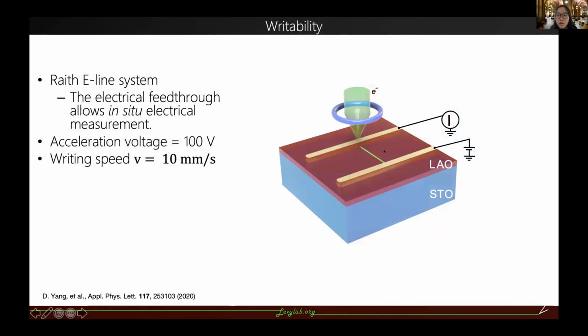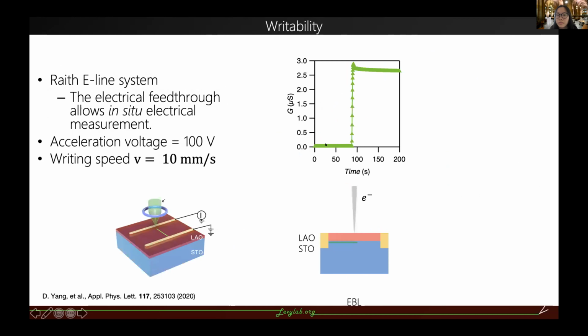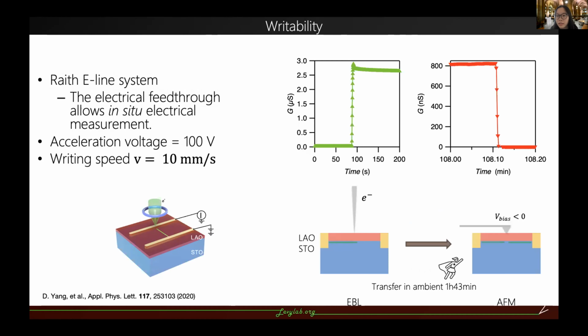This is to show the writability of this method. We have electrodes at the interface, and we expose a nanowire connecting these two electrodes using ULV EBL. With this writing process, we can observe a conductance jump from the writing. This is in situ monitoring. We added an electrical feedthrough to the SEM so that it allows in situ electrical measurement during the exposure. This writing process is also reversible. When I transferred it into an AFM and applied a negative voltage to the AFM tip to erase it, the device could be erased totally.